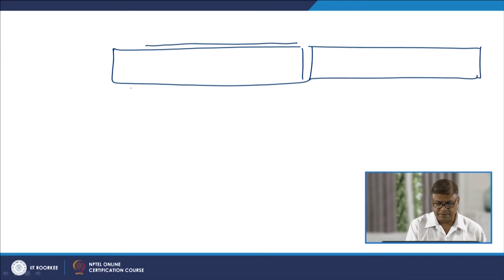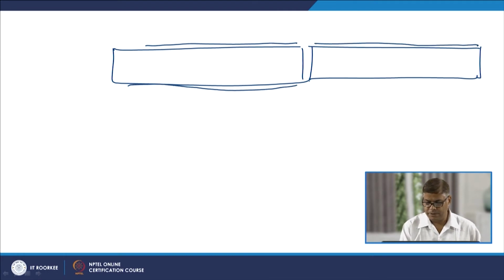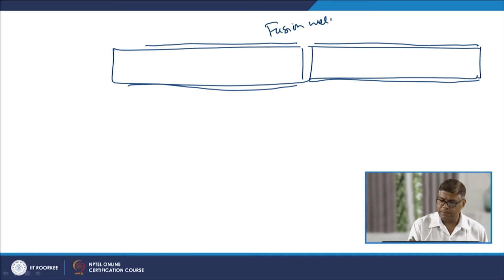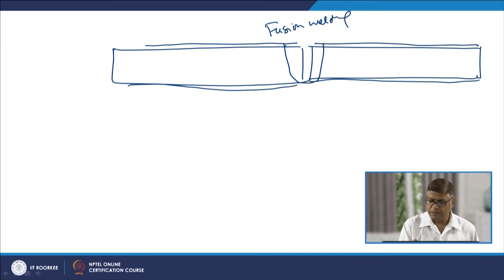that will bring a lot of difference in terms of the weldability. Zinc coating is there on both the sides or surfaces of the steel plate, and when these are welded using fusion welding processes, we will be melting both the faying surfaces of the components to be joined, and this in turn leads to the presence of zinc in the weld metal. The presence of zinc in the weld metal is troublesome, because zinc has very low solid solubility in iron, and so even in the liquid state it tends to segregate at the grain boundaries.